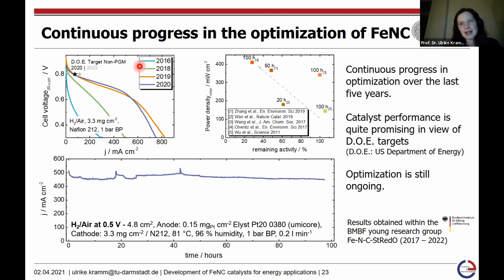First of all, there is work from Karl Mayrhofer and Frédéric Jaouen related to the online leaching rate. But there is a caveat, because this was performed on a catalyst prepared at 950 degrees C, but without acid leaching. Based on 15 years of experience with the preparation of this type of catalyst material, there are some side phases inside. So it is quite hard to know to what extent the iron leaching you can see is related to these side products, or whether it is indeed coming from the FeN4 center. One would need to repeat this for a catalyst which is acid leached in advance, in order to see the true leaching rate during operation.